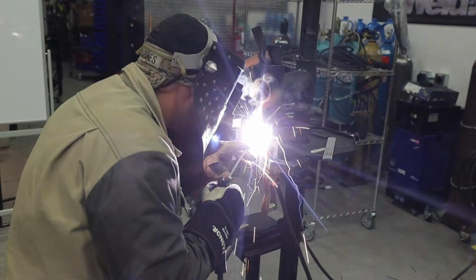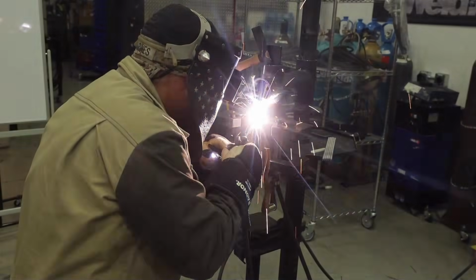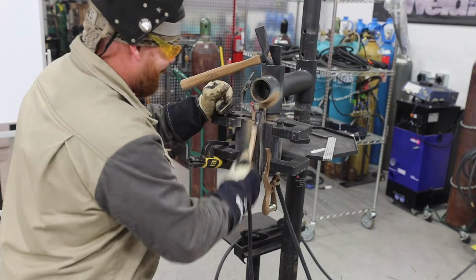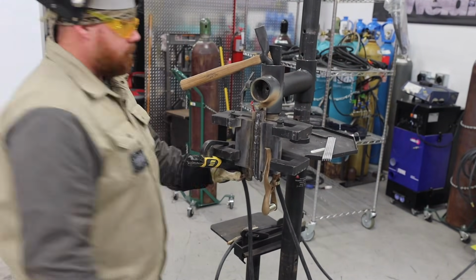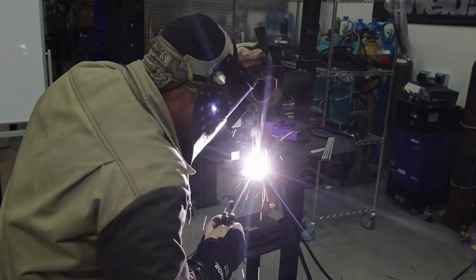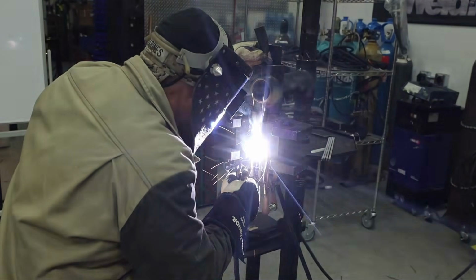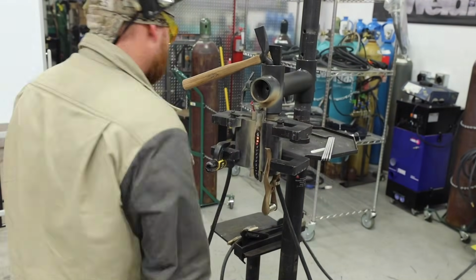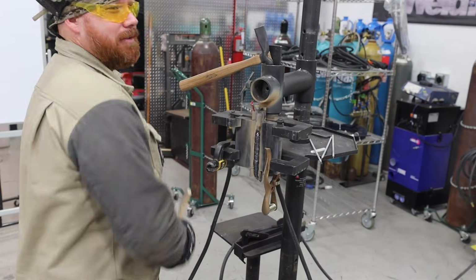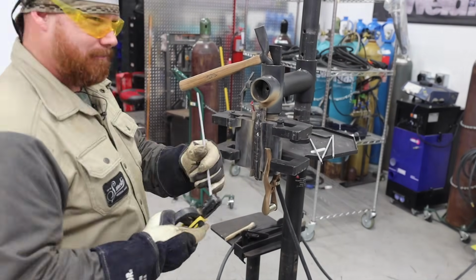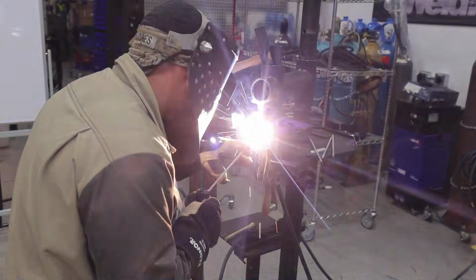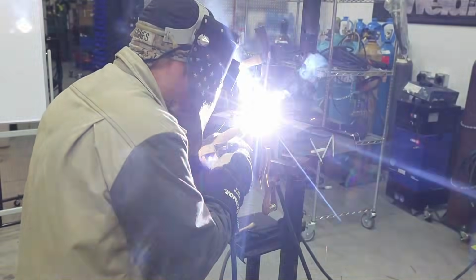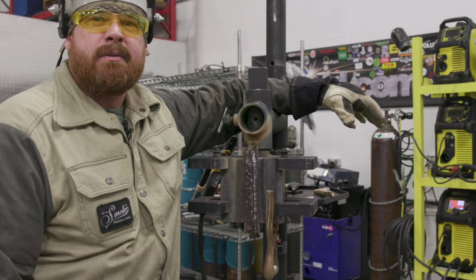I want to maintain a good interpass temp so I'm not losing control of that puddle. The more welds I put in here, the hotter it's going to get. So I'll probably put 2 more passes in here, then let it cool for about 5 minutes. That should bring me back down below 350, and then I'll throw that next course in there. Usually if you get it below 350, you can run 3 or 4 passes and then you shouldn't have to worry about it. Good to go.